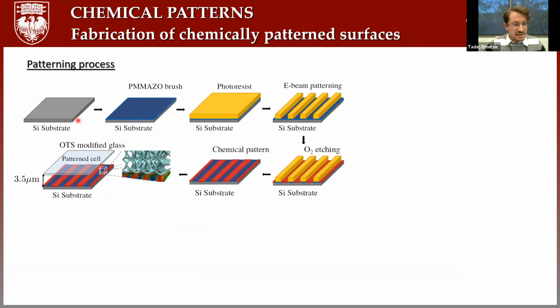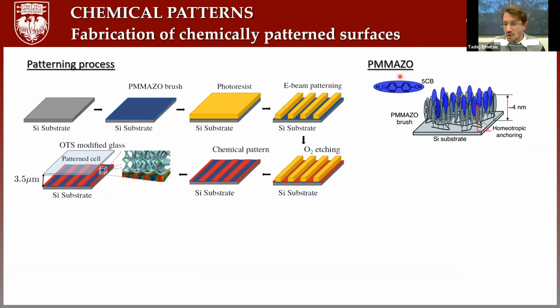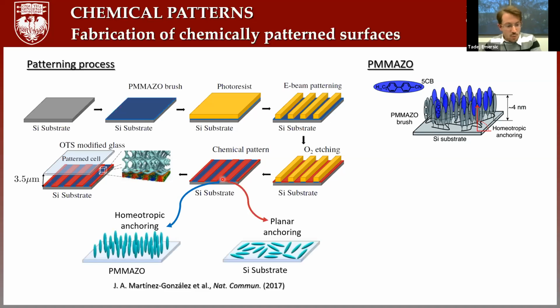So we make patterns on the silicon substrate in this way: on the silicon substrate, we first deposit PMMAZO brush. This is just some kind of polymer that dictates how the liquid crystal molecules behave on the surface. And we want that with the brush, we achieve homeotropic anchoring. And then with the process of nanolithography or e-beam patterning, we make some kind of final product. So we make a silicon substrate, as we can see here, with these alternating regions where the brush is. So here we have homeotropic anchoring, so molecules are perpendicular to the surface.